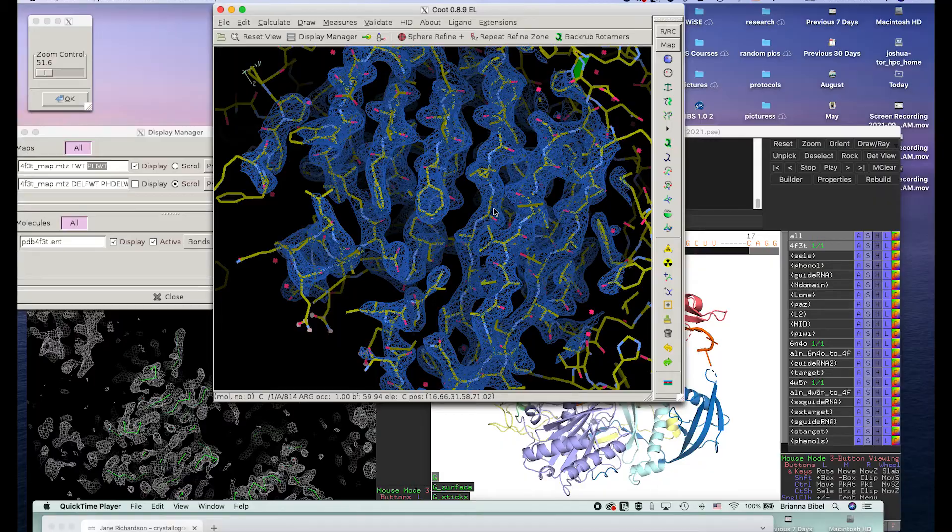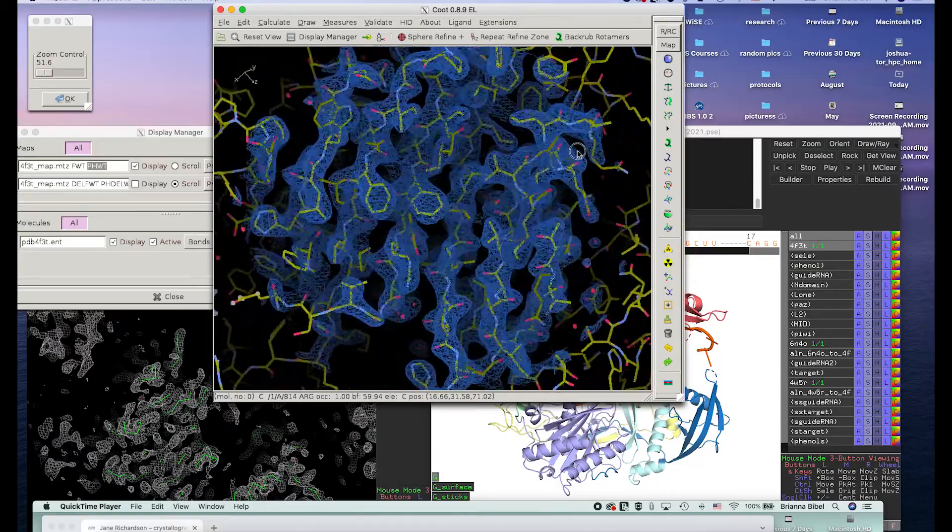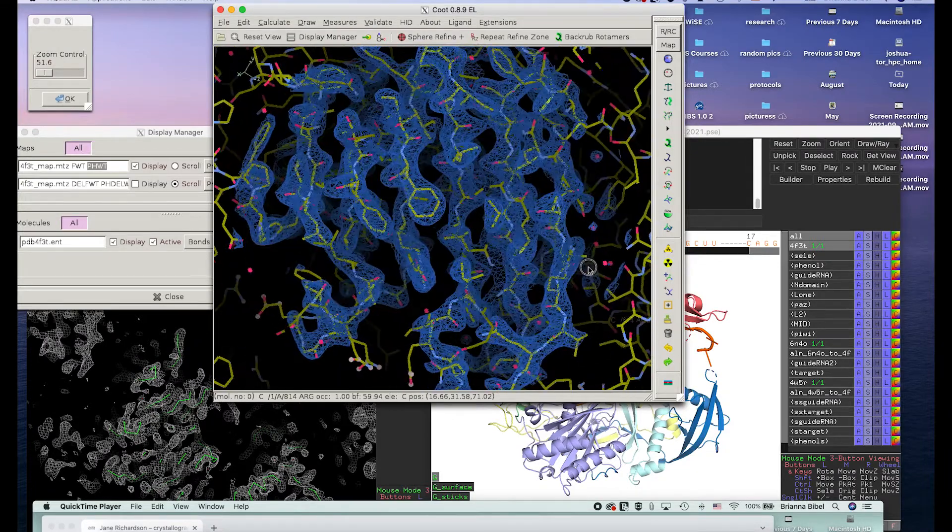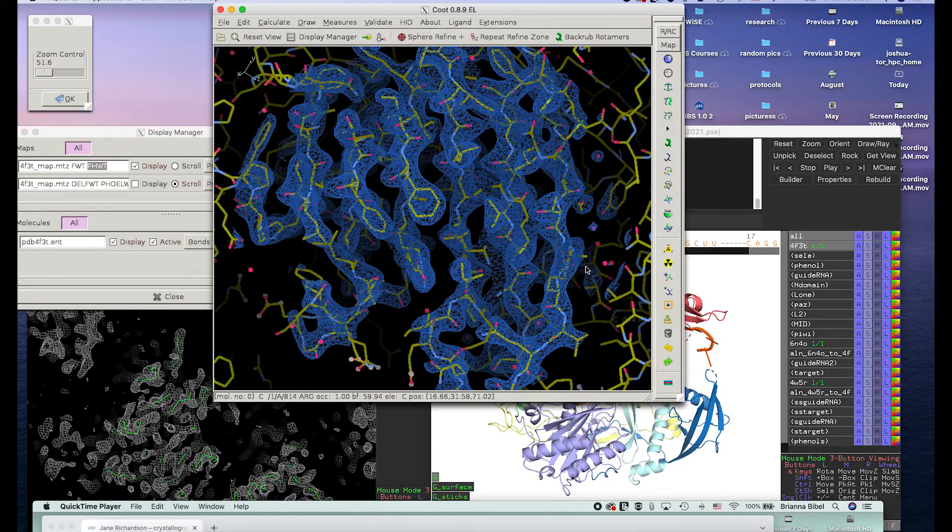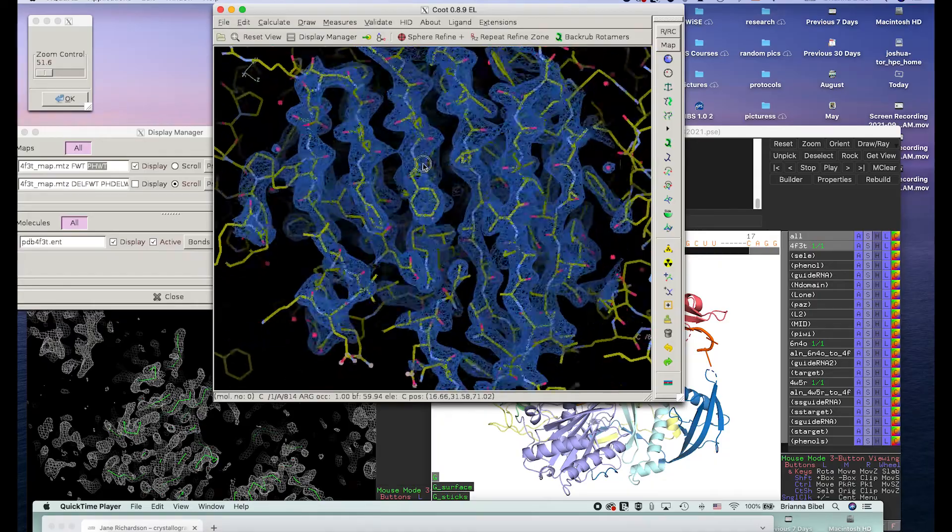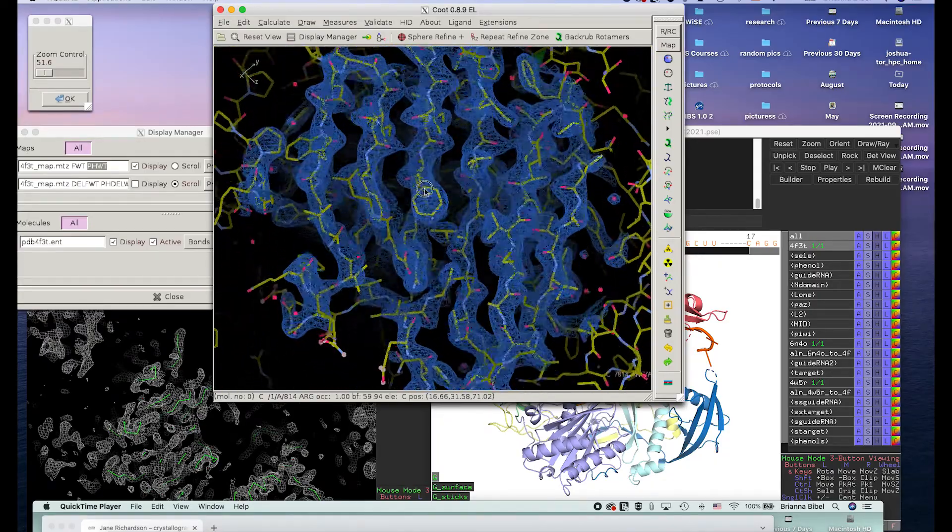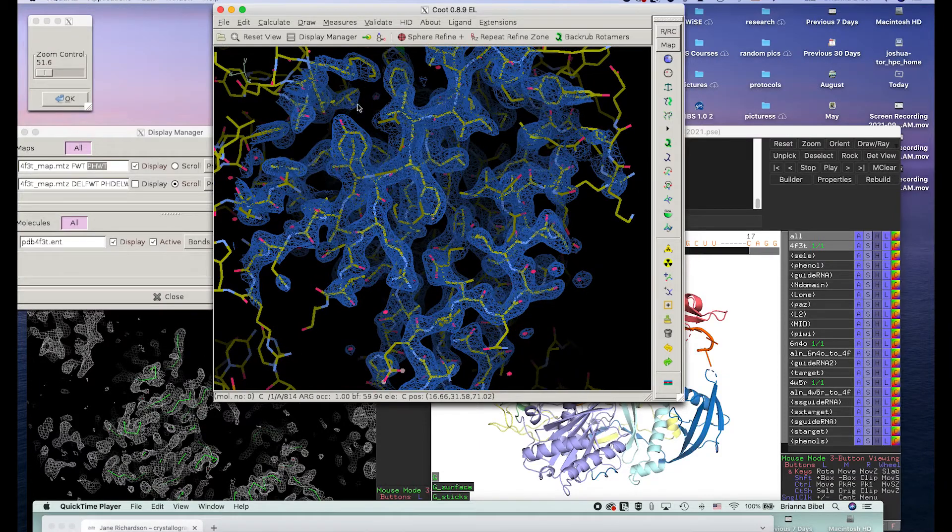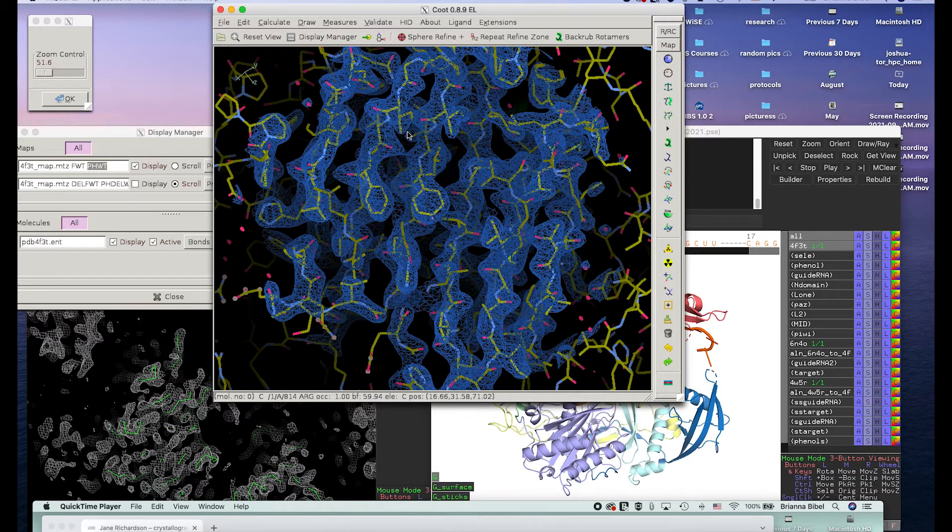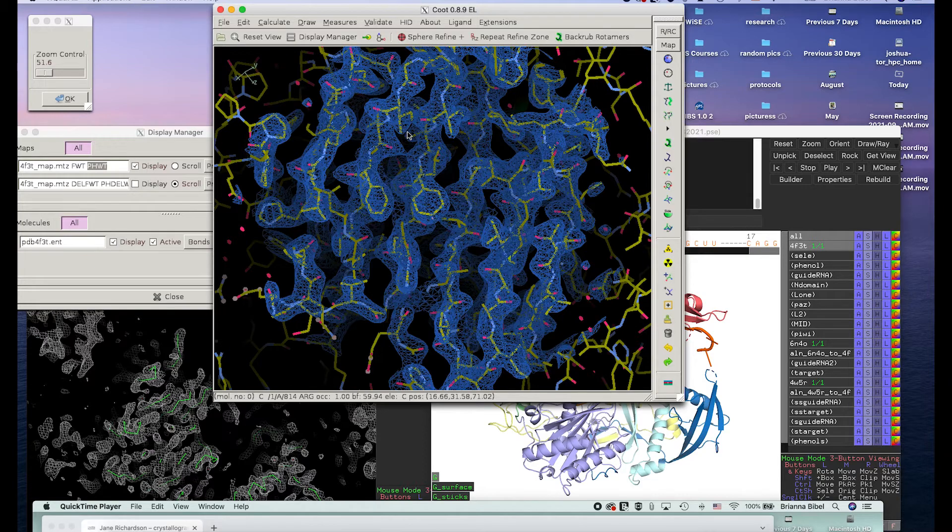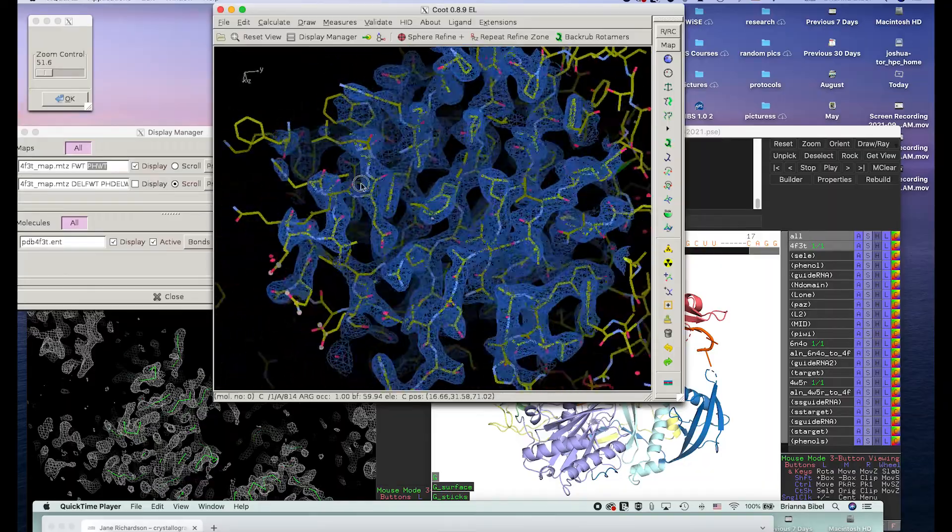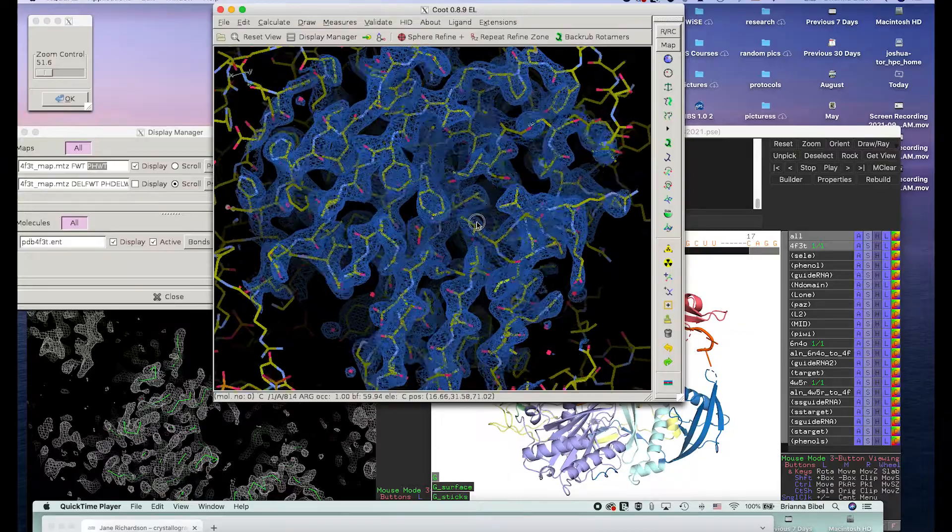But the tricky thing with crystallography is because you don't have those phase information, so you're actually refining the phases as you go. So the map can actually get better when you're working. Because remember, you only have those intensities and you're trying to figure out the phases. And so when you're working in real space, so you're fixing the side chains and that sort of thing so that they fit the density better, and then when you improve, then you go back and you calculate, okay, now what would the model, what should the structure factors and all those things be? And then you can improve the phases that way, and making sure that you also have that data that you left out so you make sure you're not overfitting.